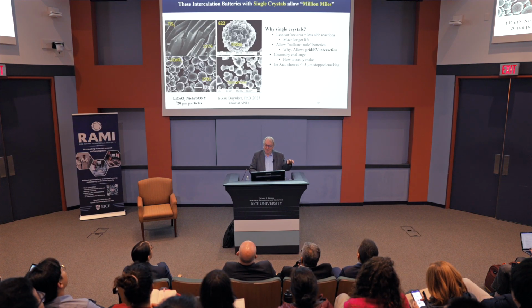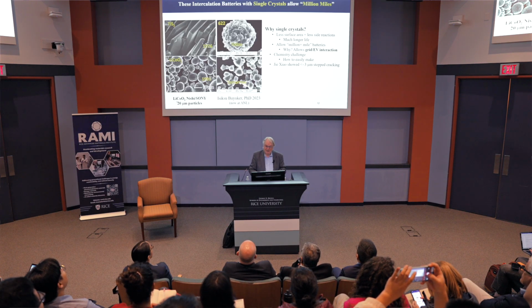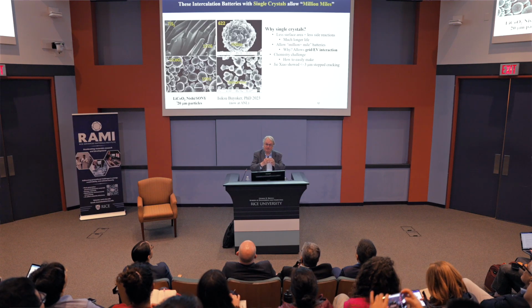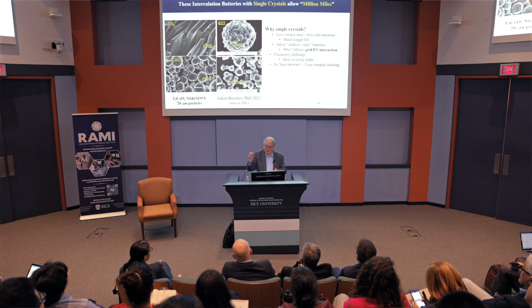The challenge we have today is how do we make large amounts of single crystals? It's not so easy. And I said these materials expand and contract by about 10%. If you keep the crystals below a certain size, about 3 to 5 microns, they will not crack. The meatballs always crack, because you can understand they're expanding by 10%. If one's like this, it tries to expand, it will crack all the joints between the others. When it cracks, then you get reactivity with the electrolyte there.